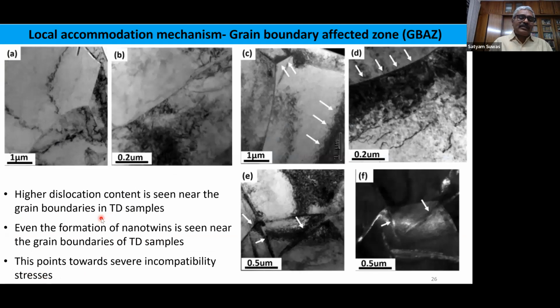And we also did transmission electron microscopy to see whether the observations that we had from EBSD and KAM analysis are true or not. And we could indeed see that in the case of the TD samples, there is some accumulation of dislocations here at the interface, which was reflected in EBSD by higher KAM regions.